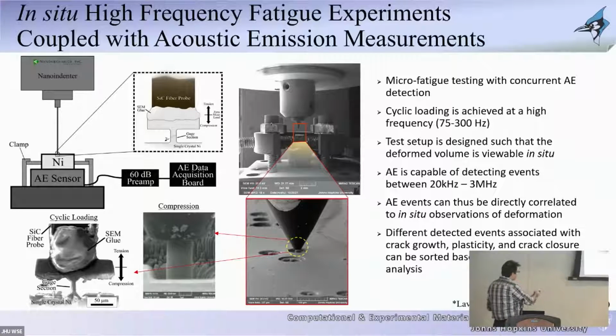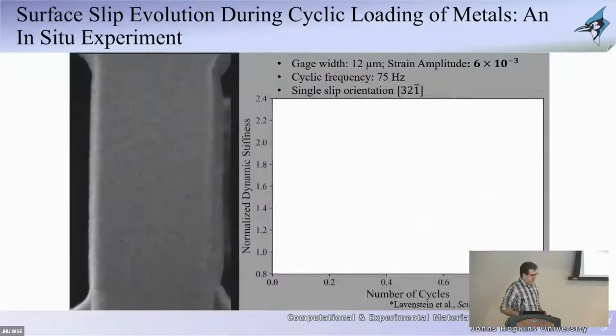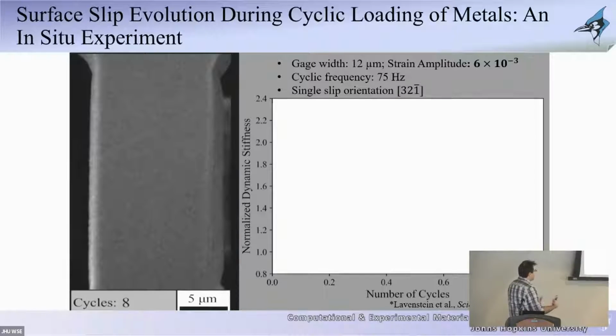What I'm going to focus on for the first part is this idea of cyclic loading inside the SEM. So we fabricate these dog bone-like specimens, and what we're interested in is really what happens at that specific spot, which is the gauge section. So this is actually a real experiment that I'm showing you here. So this is the sample, and what you're going to see at the bottom here is a counter that basically indicates that we're increasing the numbers of cycles. Cycle basically means it's a fully reversible tension compression cycle. This is done live inside the SEM. The surface is not entirely clear because there's some small vibrations, but you can vaguely see formation of lines that are forming on the surface over there.